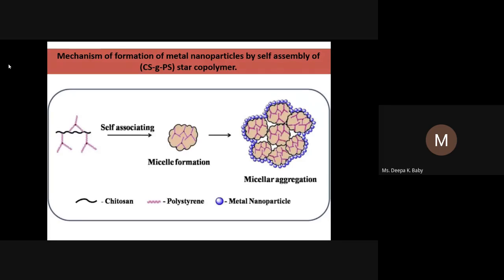And this is how it undergoes self-assembly, and how the nanoparticle is formed in this chitosan polystyrene copolymer. By self-assembly, this polystyrene chitosan will form a micelle. I told you earlier that chitosan contains hydroxyl groups and NH2 groups. When the metal is added in bulk, it will react with these NH2 and OH groups and form a bond with chitosan. After that, since micelle formation takes place, this metal is entrapped inside the micelle, and as a result, separation of particles takes place. And this is how you get nanoparticles in the chitosan polystyrene micelle.